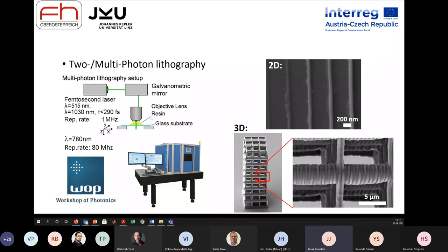And when we focus them into our resins, this is what we can achieve. The feature sizes are around 200 nanometers or even 100 nanometers. And when we write 3D structures, structures of around several micrometers can be structured. And when you look at it closer, here you see nicely the point spread function, which has been basically polymerized into the volume of the monomer.